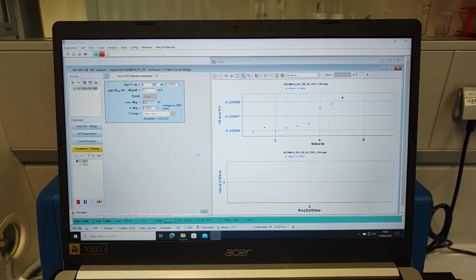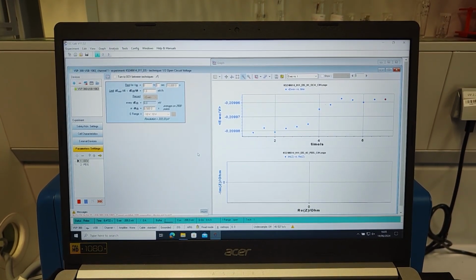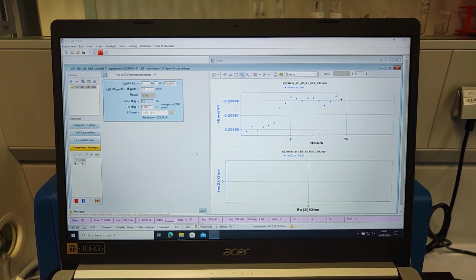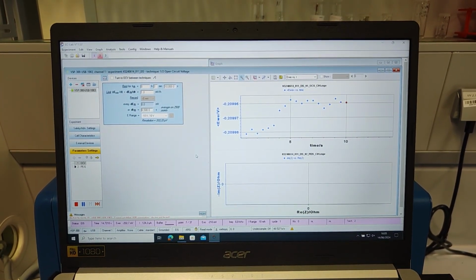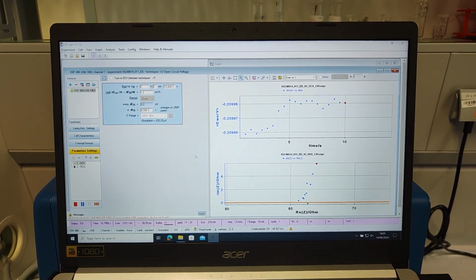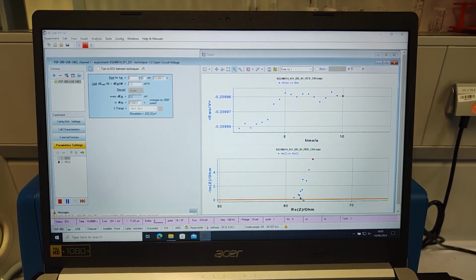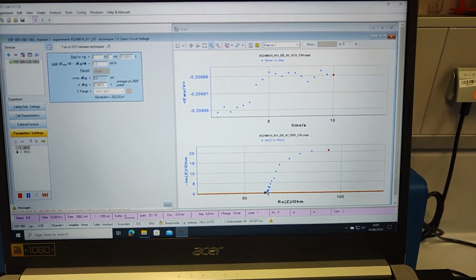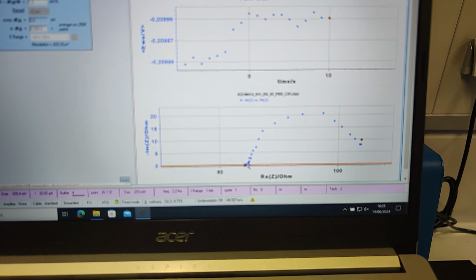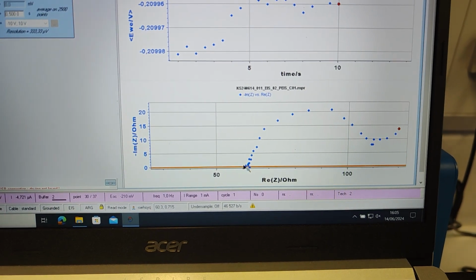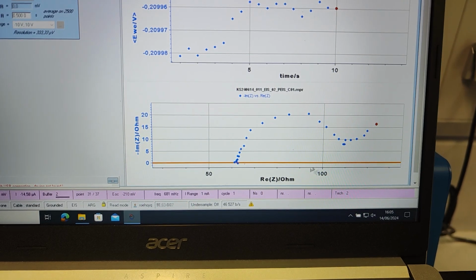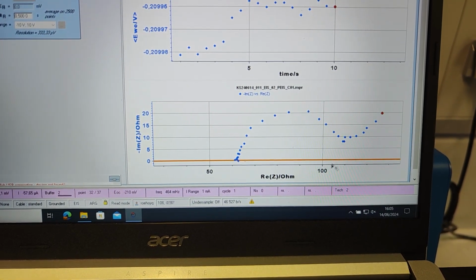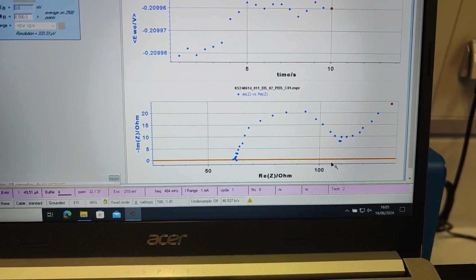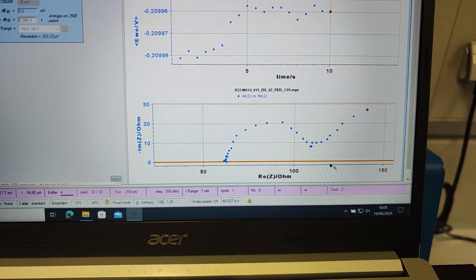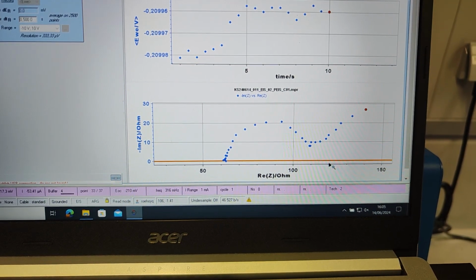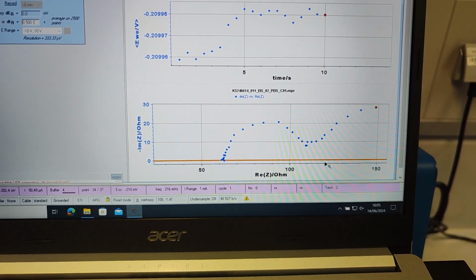Okay, as always, we start with an open circuit voltage. And now the impedance starts with a real axis offset of around 60 ohms, again forming a semicircle with a diameter of around 50 ohms. And this is then transversing to something that looks like a 45-degree line again. We are measuring from 100 kilohertz to 100 millihertz.